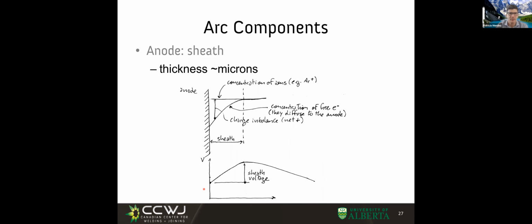Let's talk about this sheath. I put microns here, but it's submicron, the thickness. What happens, the anode is positive, and we have all this plasma, in which we have these ions and electrons that are loose. And really, right next to the anode, the plasma is, say, 20,000 Kelvin out here, right? We have anode here and deep into the plasma. And here is the plasma at 20,000 Kelvin, more or less. The anode, whatever material it is, is not going to be at 20,000 Kelvin. The anode is typically 2,500 degrees C for molten steel, could be 3,000 degrees C for tungsten, right? So it's much less. 20,000 Kelvin out here, more or less 3,000 Kelvin in the anode.